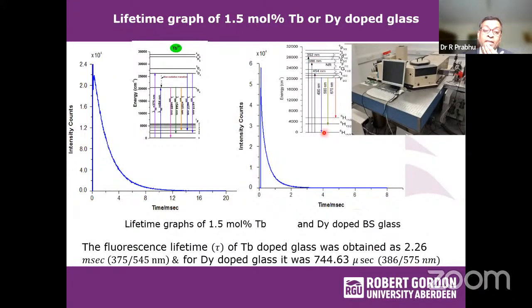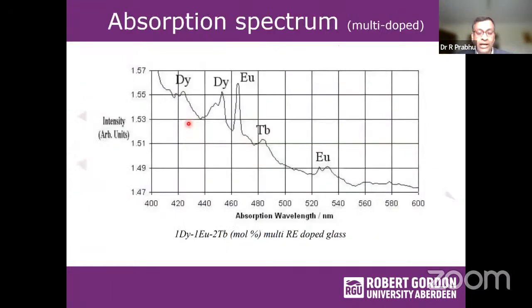So these lifetimes are specific to these rare earth elements, and these lifetimes might change based on the host matrix. So that provides an additional security feature for these elements, or security feature overall. Now, that was single doped glasses, while again we tried multi-doped glasses to enhance the combination of spectral signatures. We doped dysprosium, europium, and terbium together to form the borosilicate glass.